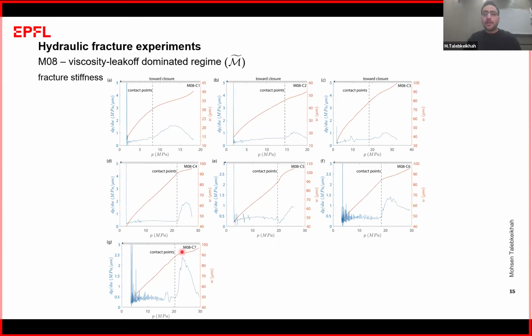So here, for each cycle, I plotted the stiffness versus pressure, and we could see that, as I mentioned before, there is a kind of linear behavior in the stiffness exactly at a specific kink point. We can see a linear behavior, especially on this cycle. You can see it is exactly linear. Here it is completely linear.